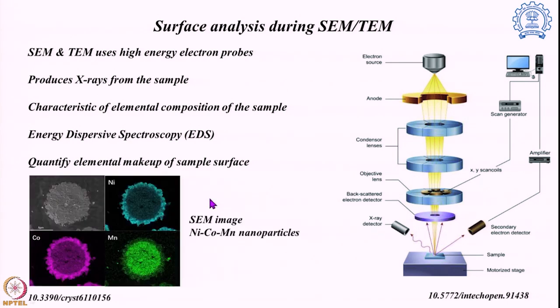So there is an example. Over here I am showing you SEM data first, this picture in this gray region, which actually contains nickel, cobalt and manganese. And then we did that EDS study along with that, and this particular bluish color over here shows you the presence of the nickel, and you can see the nickel is mostly present on the edge, almost a very negligible amount in the middle.